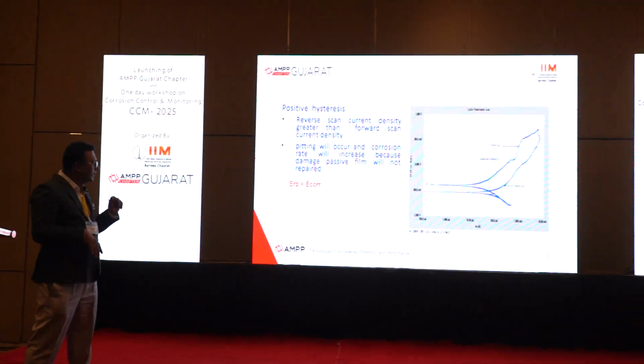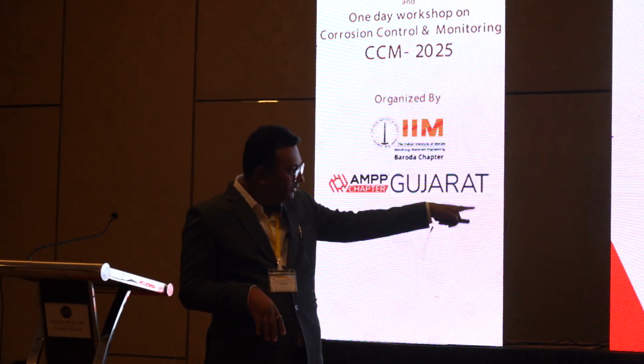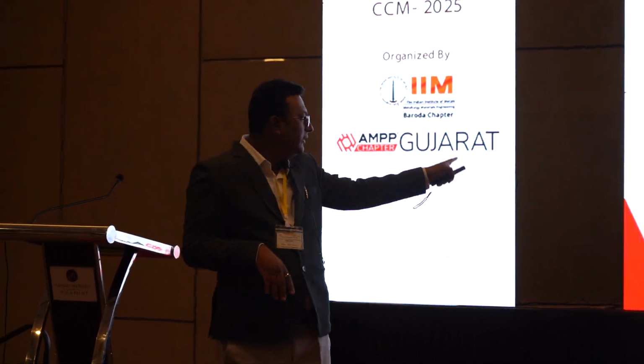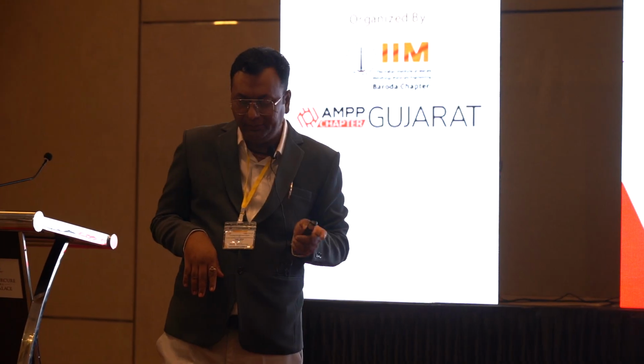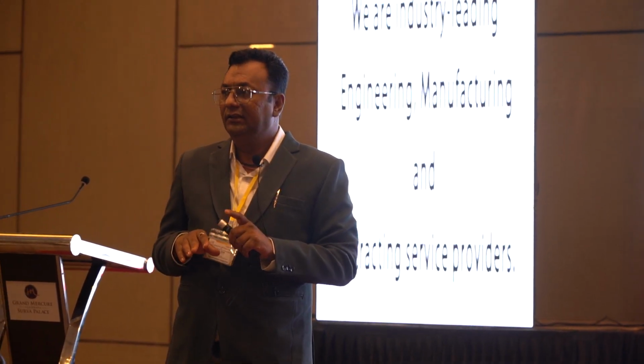But if it is reversed, when it intercepts on the lower side in the active domain, when ERP is less than E-corr, the repassivation point is lower, and that is just like uniform corrosion. We saw the number of pits in stainless steel during the presentation by Mr. Hire. Stainless steel gets a number of pits in chlorine environments. When stainless steel gets pitted at a number of locations in a chlorine environment, you will get stresses, and that is a quick failure.